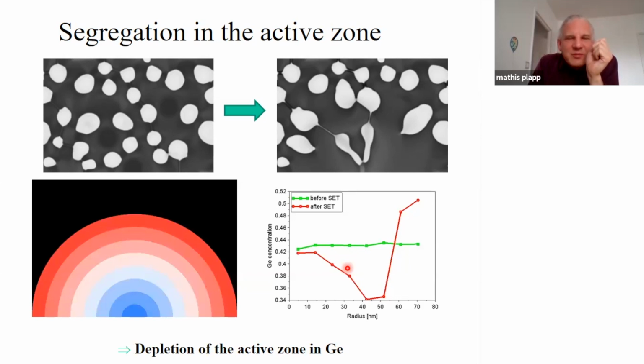And what happens is that the temperature goes down so fast that the phase field mobility goes down so fast that the interface at some point just stops, and the core of the active zone remains amorphous. So the model can correctly capture the transition between the amorphization and the crystallization dynamics. And that means you can study the influence of the current pulse. And that's something that interests the engineers, because in principle, you could vary the composition and then you could play around with the current pulse and see what the model predicts.